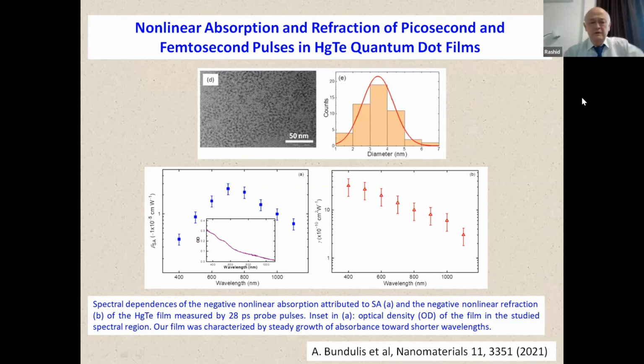which have shown the spectral dependence of the nonlinear absorption process, which is saturable absorption, and nonlinear refraction. This dependence is also important to understand where the nonlinear optical processes could be used most efficiently. Particularly, the saturable absorption was observed at roughly 700 nanometers as the strongest nonlinear optical effect. Thus, correspondingly, it could be used for the mode locking of femtosecond lasers in this wavelength range.